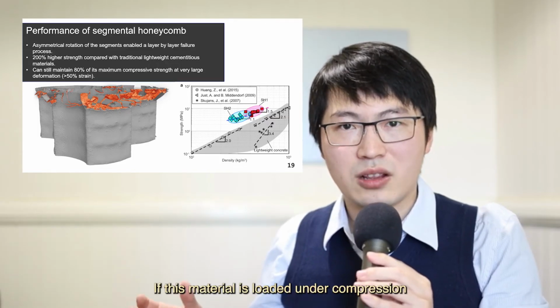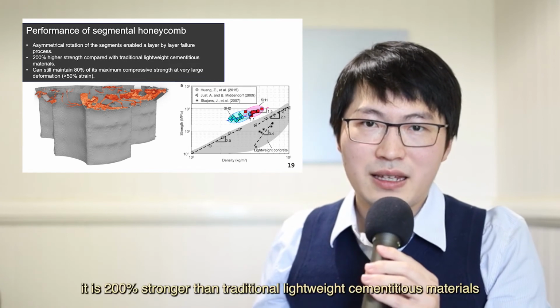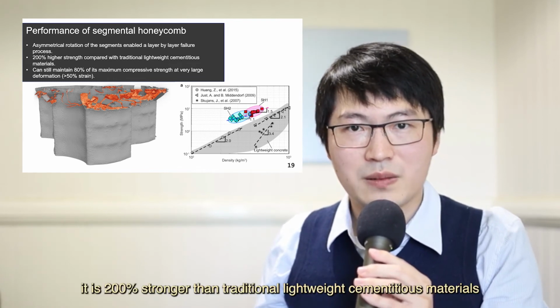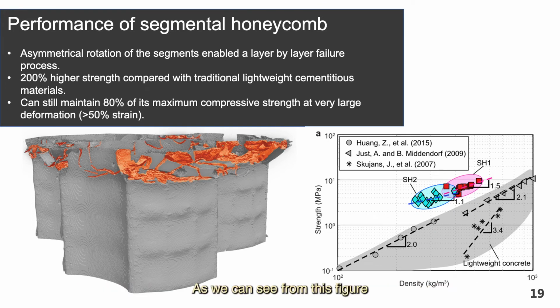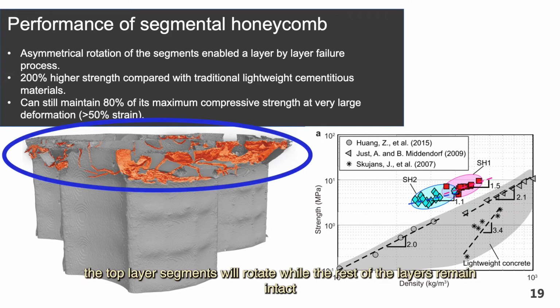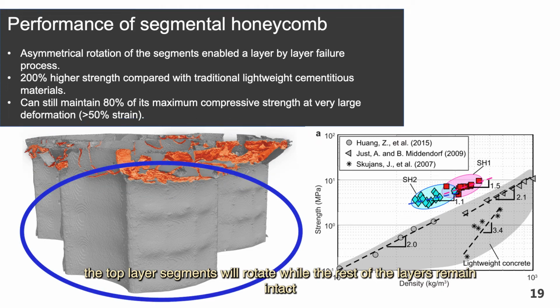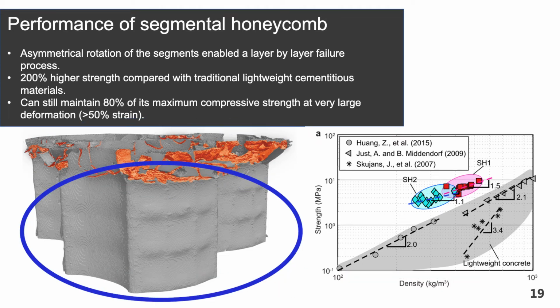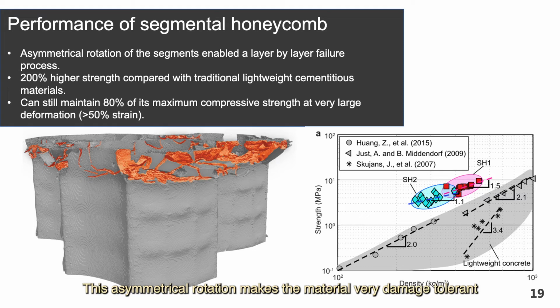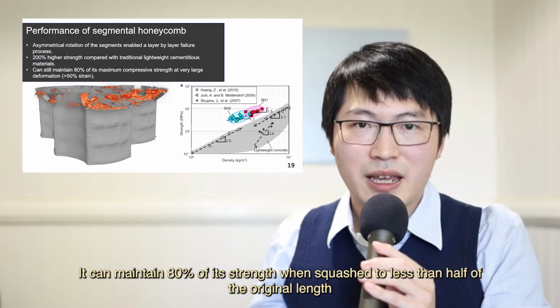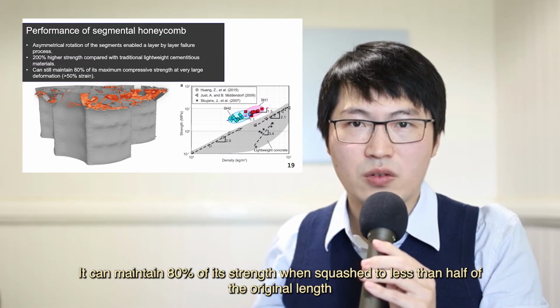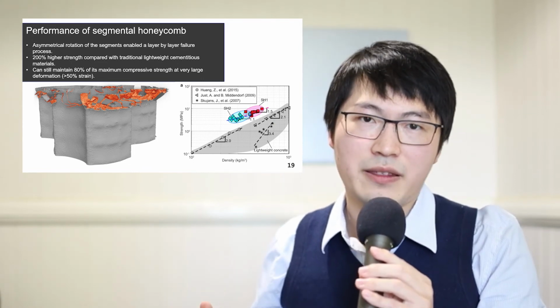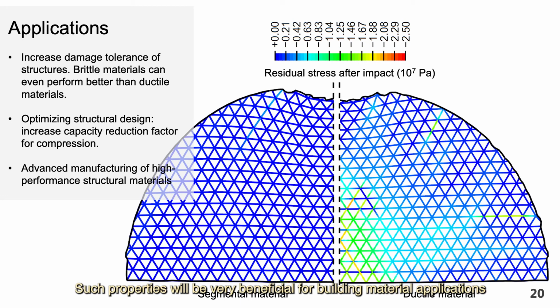If this material is loaded under compression, it's 200% stronger than traditional lightweight cementitious materials, as we can see from this figure. When the force is too large, the top layer segments will rotate, while the rest of the layers remain intact. This asymmetrical rotation makes the material very damage tolerant. It can maintain 80% of its strength when squashed to less than half of the original length. Such properties will be very beneficial for building material applications.